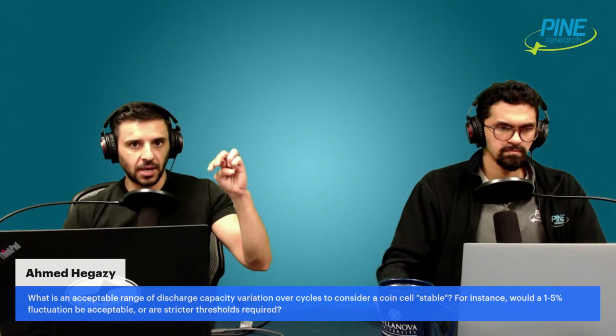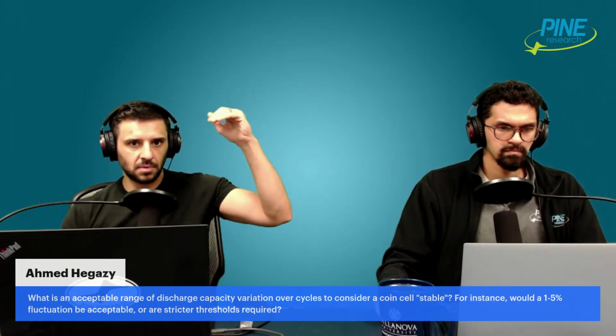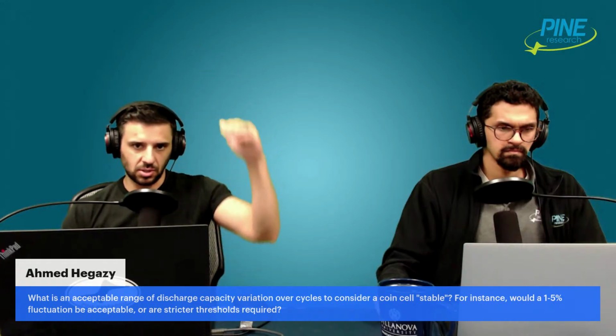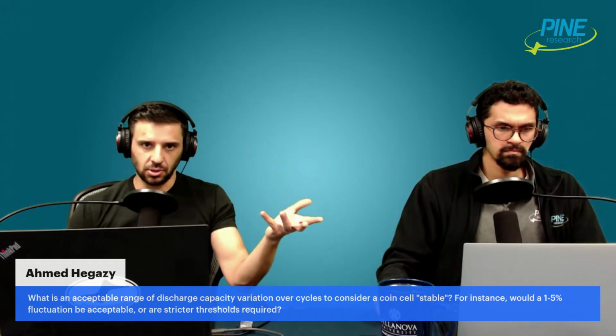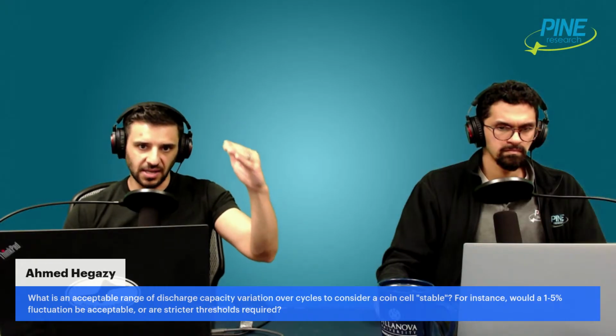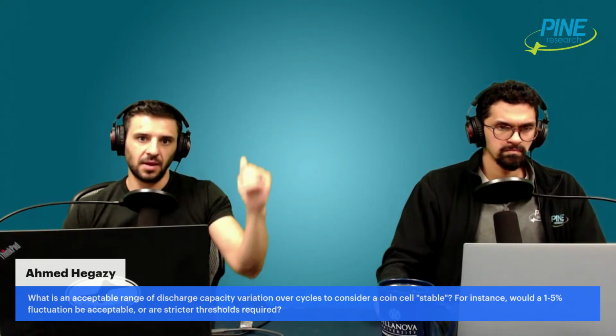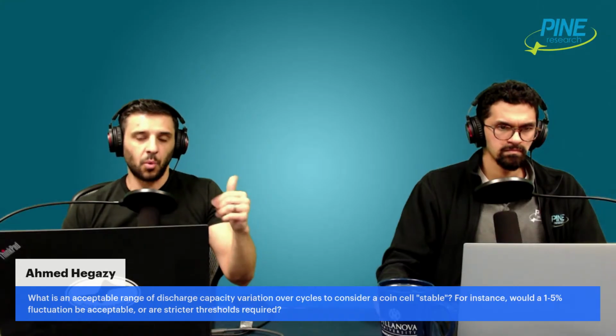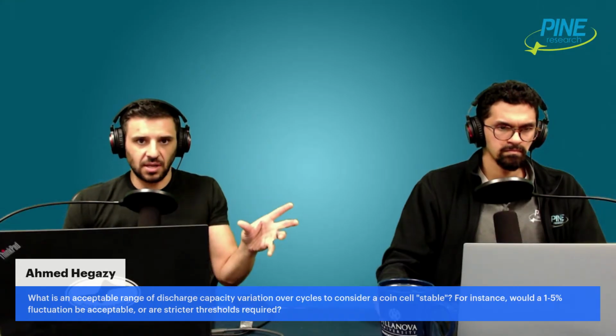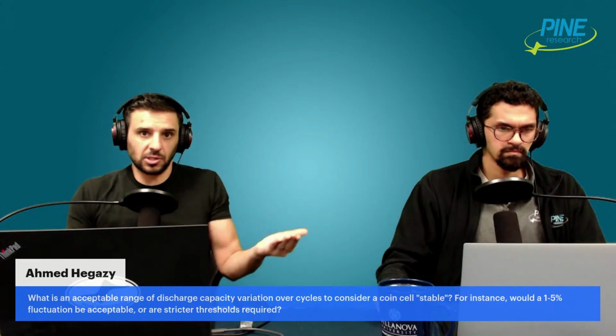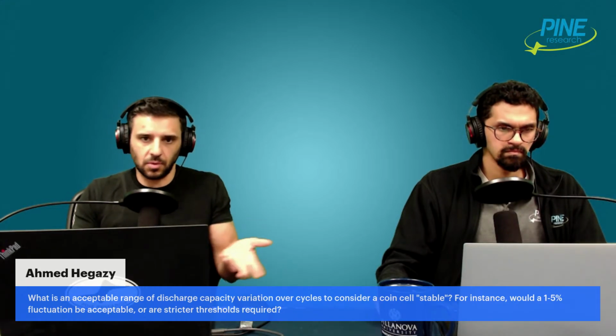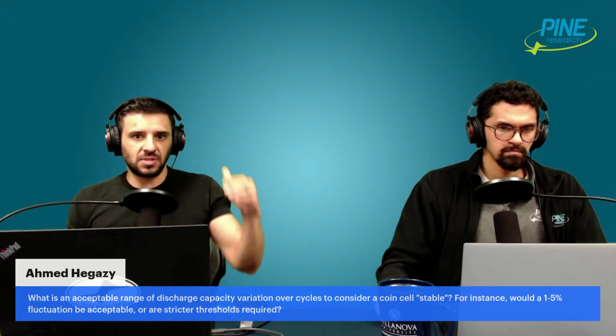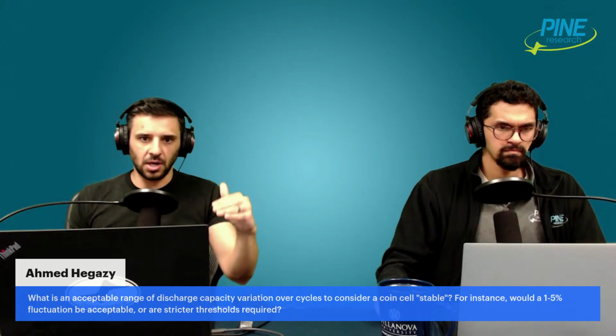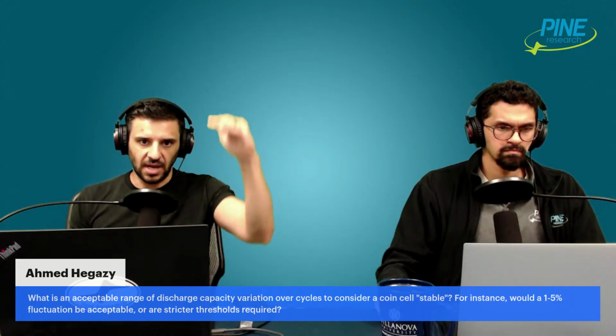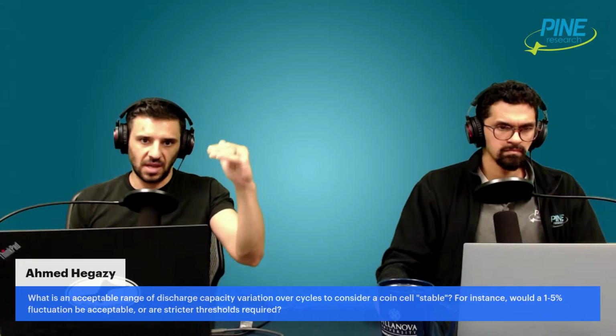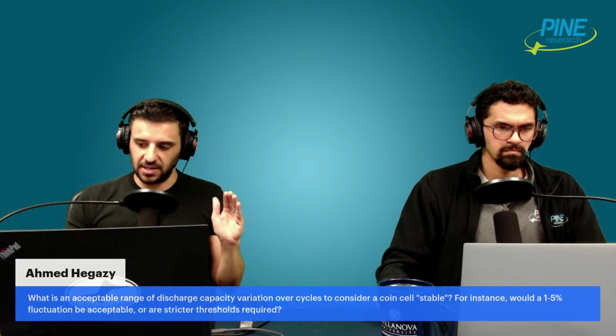And I'm not talking about, okay, you charge up and then you discharge, and let's just say it's 100 milliamp hours, right? And then the second one, you get 97. And the third one, you get 93. And then the fourth one, you get 86. Well, that isn't deviation. That's deactivation. Maybe your material's poor, which is fine. You're learning something about your material. It's okay. But if you do 10 charge discharge cycles and you get 100, 115, 92, 107, 86, that's a problem. That is definitely a problem.